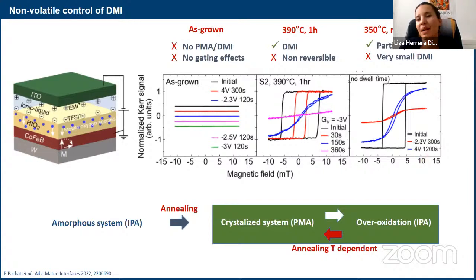We could see that at some point you have to anneal, and even if you anneal at lower temperatures for very short times, it will still not be enough. So it seems that crystallization is not really good friends with ionics, because you have a harder time moving ions back and forth. I told you already at the beginning, reversibility is an issue, or can be an issue, for magneto-ionics. So we really wanted to see reversibility in cobalt iron boron systems.